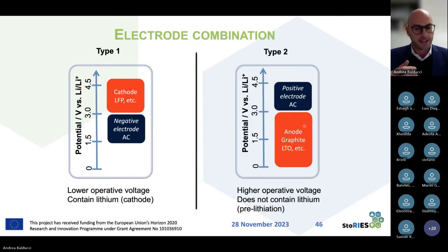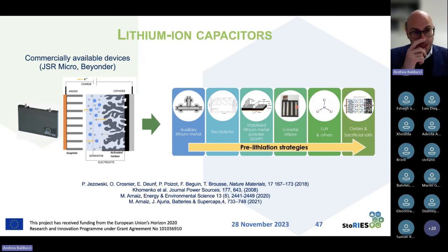The problem in this system is that when you assemble them, what they are missing is the lithium, because to work, graphite needs lithium, but activated carbon doesn't have lithium. So what you need to do is to find a way to bring these electrodes together and to bring lithium into them so that they can operate as lithium ion. These systems are actually available, and are called lithium-ion capacitors. There are companies like JSR Micro or Beyonder that are producing them. And these systems rely on graphite and activated carbon.